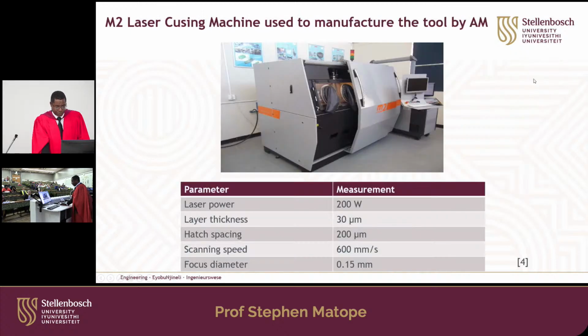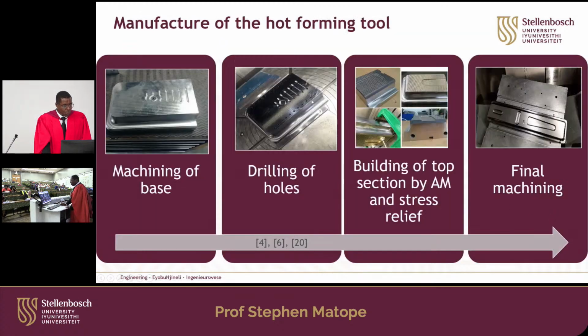Now, the machine which we used is our M2 laser cusing machine. With this tool, at one time, it was actually the best of the two in Africa. That's how our technology had really grown, but unfortunately it's a bit down now in some benches. But we are fortunate that whilst it was still in its useful time, we managed to use it, and those were the parameters we used: the laser, the layer thickness of 30 microns, the hatching and the like.